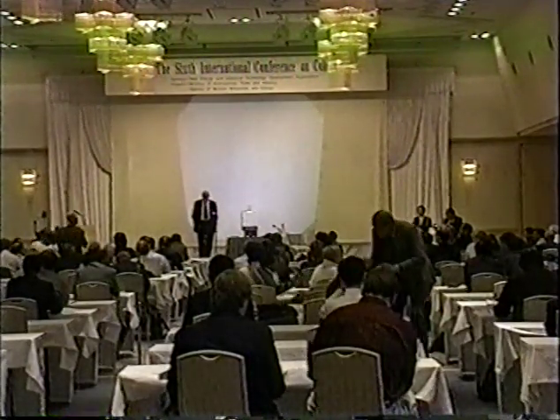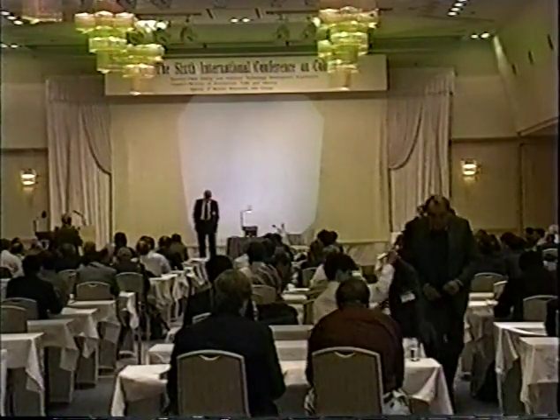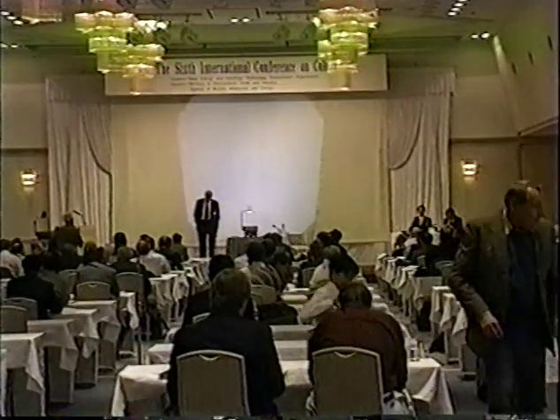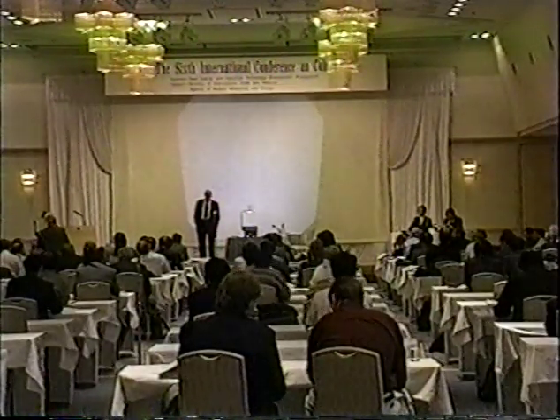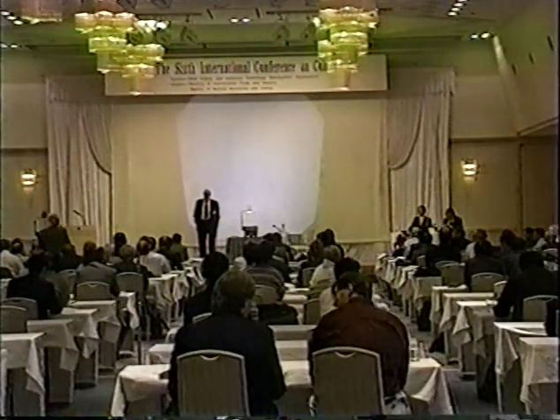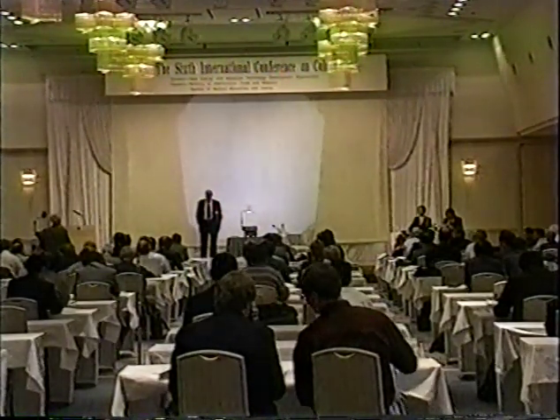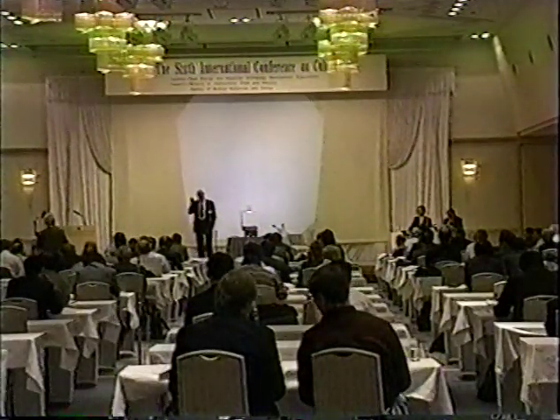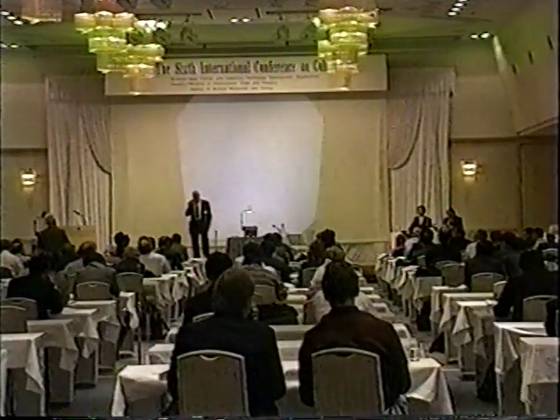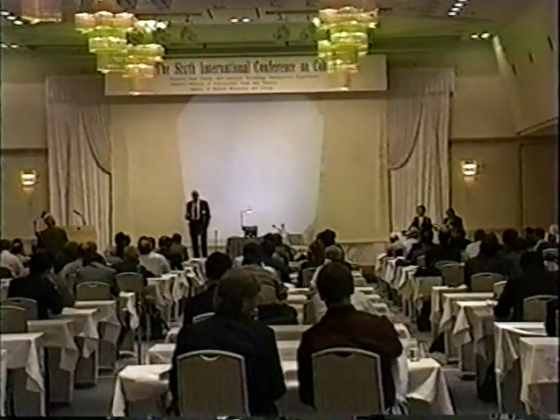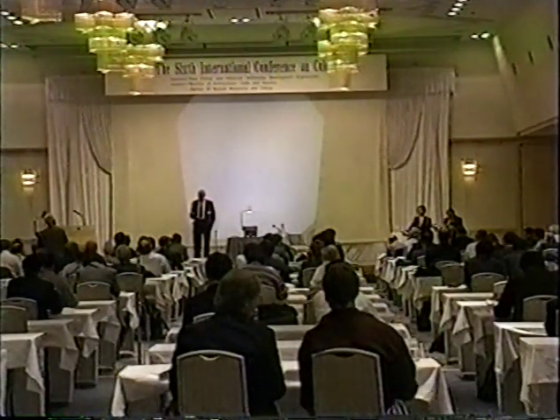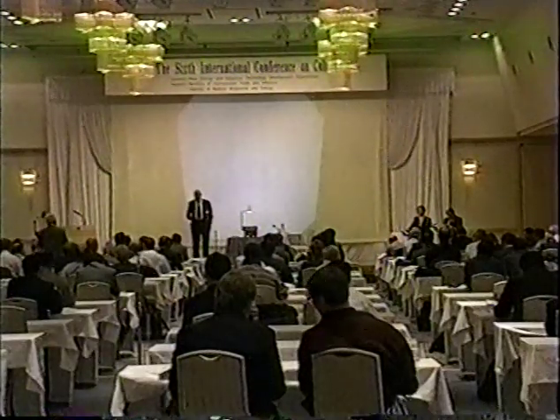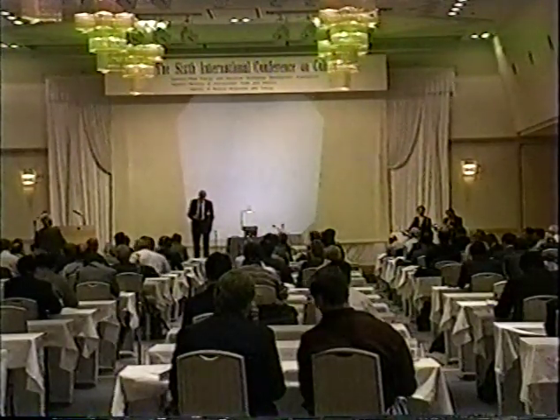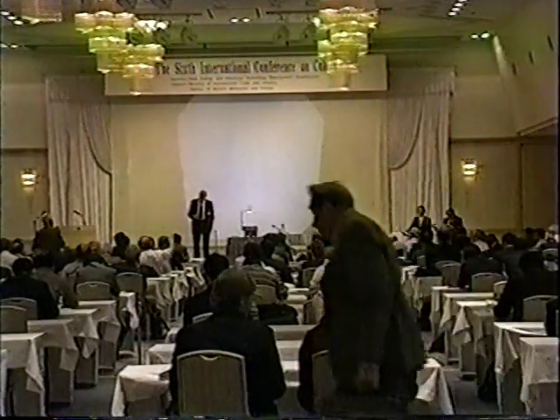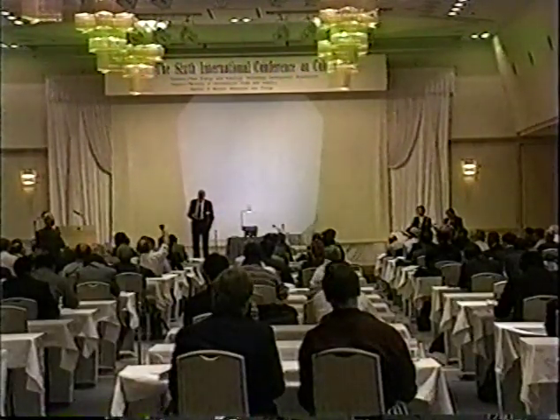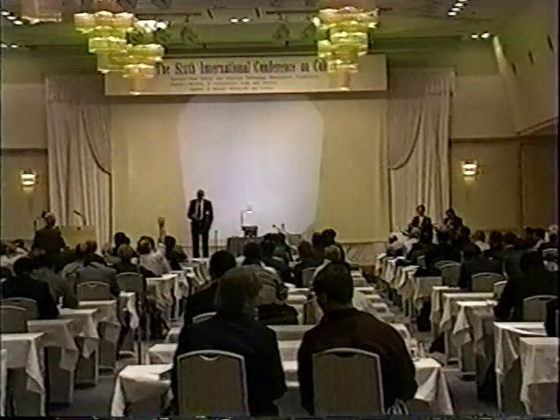I believe you said that you get information from the initial thickness of the sample, is that right? Yeah. Okay, which means then that your fear about the leaching of boron is not really well founded, because it is only to the surface. I hope you're right, but it is only 25 microns thick, and it's being leached from both sides. It's immersed, you see. So I was suspicious that we might have that, but if so, we will check it by having the anode, which is similarly immersed, in the same thickness. In addition, you would believe that the interesting nuclear reaction occurs on the surface only, and then you're diluting your measurement of the initial thickness. That's right.